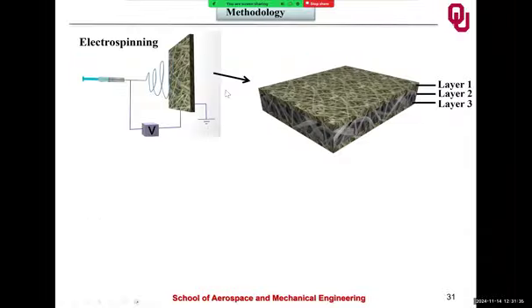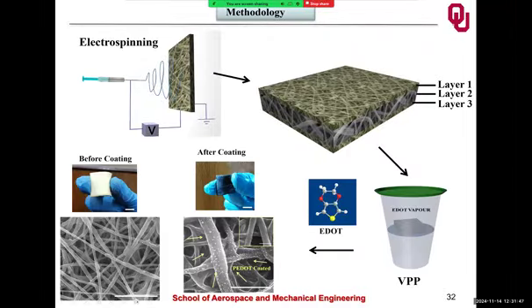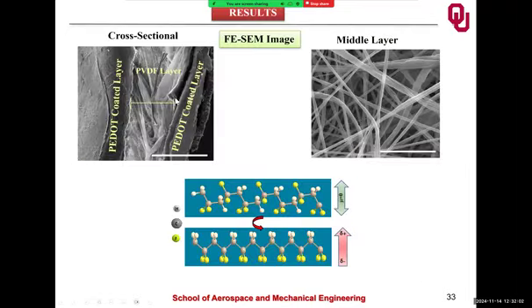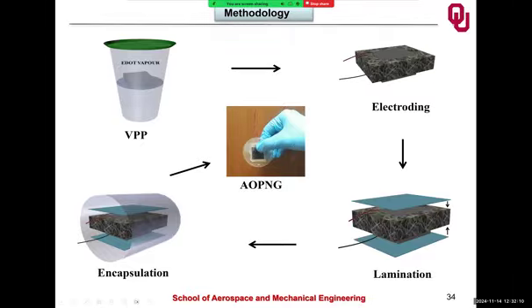Let's see, first we did electrospinning and we get different layers, like 1, 2, 3. The first and third layers should be coated by the conducting polymer, that is PEDOT. Here's an example after coating; this PEDOT is actually a conducting polymer. After vapor phase polymerization, that is VPP, the fibers are coated by conducting polymer. And under the microscope, we can see that evidence. So this is the typical methodology. I'm not going into the details.